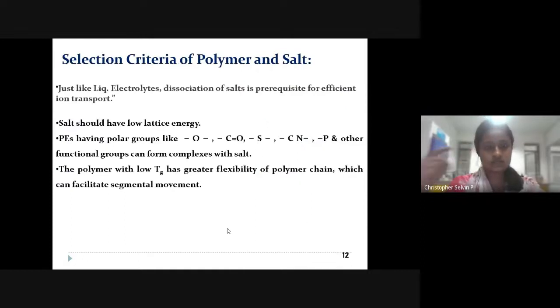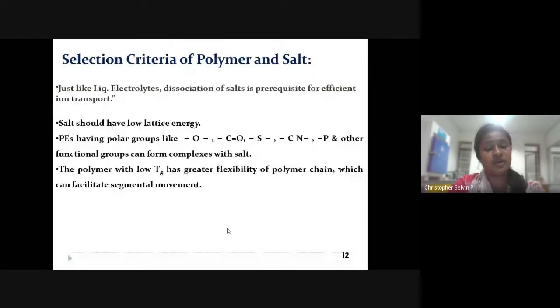So the selection criteria for polymer and salt, just like liquid electrolytes, is dissociation of the salt into its respective ions for efficient ion transport. That is, the salt should have low lattice energy, and the polymer electrolyte should have certain polar groups like oxygen or sulfur or CN, and other functional groups that can form complexes with the salt that has been added. And the polymer should possess a low glass transition temperature, so that it will have greater flexibility of the polymer chain, which can facilitate the segmental motion.